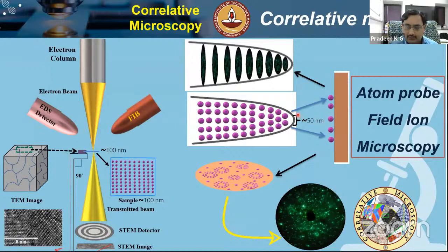On the other hand, even though we may say the shape of the tip is going to be this 50 nanometer, the electrostatic potential that is applied is over the range of a few volts per nanometer. It is still not an accurate prediction of the exact curvature of the tip and the exact potential that is being applied. It is just relative, and with a good guess, we are able to get reasonably good images.